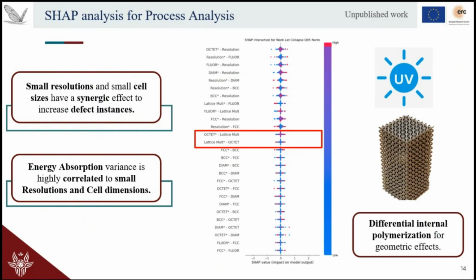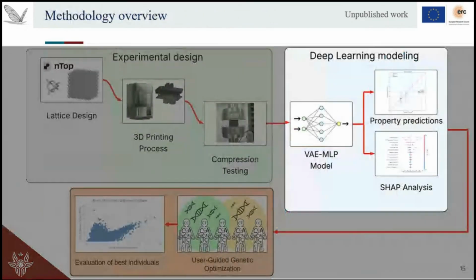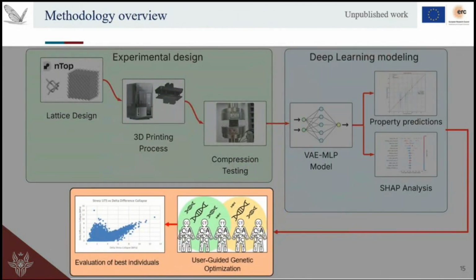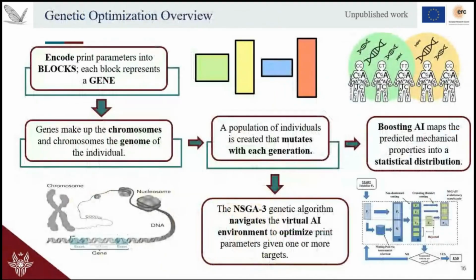But since there is a lack of polymerization essentially inside of the specimen, we are creating some buckling initiation points, and that helps increase the overall energy absorption of the lattice structure. So that's for the deep learning modelization. Now let's dive into the last part, the optimization of those parameters.